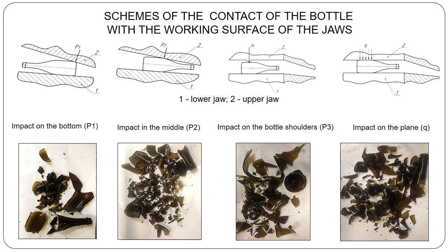The bottle can be loaded into the crushing chamber in a position where the longitudinal axes of symmetry of the bottle and the chamber are perpendicular, when exposed to a cylindrical surface by a point load. The neck and bottom are not subjected to destruction, with sufficient destruction of the cylinder. The preferred result is obtained when the surface of the bottle interacts with a distributed load Q.